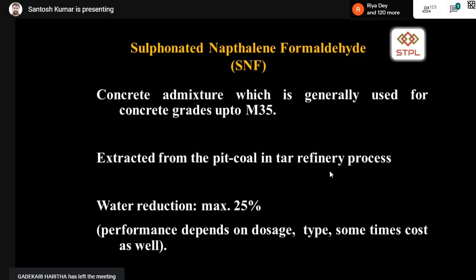And the performance of the admixtures mainly depends on the dosage of the admixture, type of the admixture, model, sometimes cost as well. See, what happens is, consider one brand of admixture, one model, they cost 50 rupees per kg. If the contractor negotiates with the admixture manufacturer, he may give it for 45 rupees, but he will reduce the solid content. In turn, it reduces the performance in your concrete. So sometimes not all the manufacturers do this, but there are many agencies who do this. So care must be taken. Whatever you are ordering should be the sample which meets your requirements in the field.